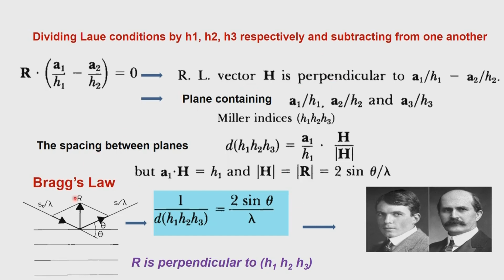The other advantage is that now diffraction can be very easily understood as though it is a reflection, and the use of the Bragg equation will allow us a direct determination of the reciprocal lattice quantities, which was probably not possible if we had used the 3 conditions of Laue. And that way practically this equation is the one which now tells us the entire geometry of the diffraction experiment which we have done. So, we not only get the information about the real space geometry, we also get information about the reciprocal space geometry, and the two geometries are related to each other.